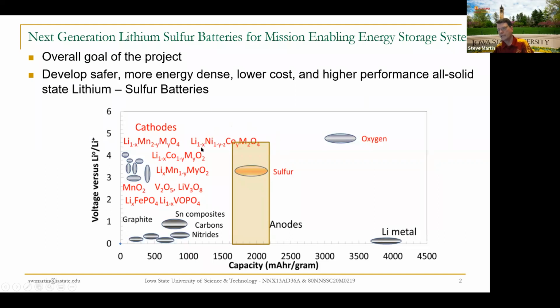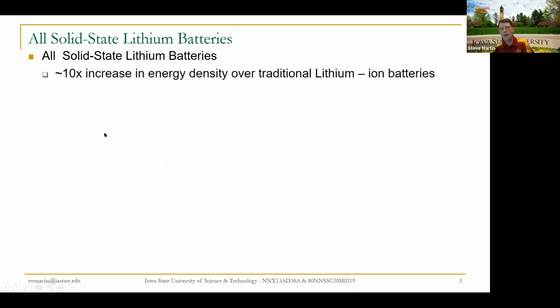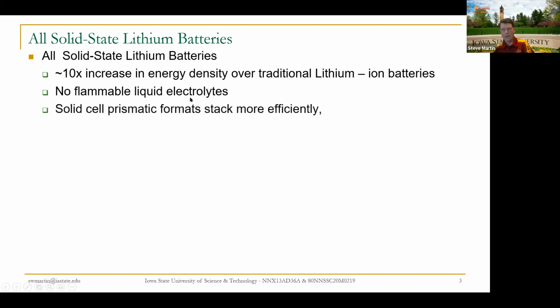But the intermediate step, which everybody is working on, NASA included, is lithium sulfur. Air has a problem for NASA because there's not very much air around in places that they tend to visit. So they use the advantage of sulfur. So our work is on developing new lithium sulfur batteries for NASA. Our particular approach is a solid state approach, where we can increase the energy density about a factor of 10, like you saw, from a 300 out to a 2000 or so. But we get rid of the flammable liquid electrolytes.